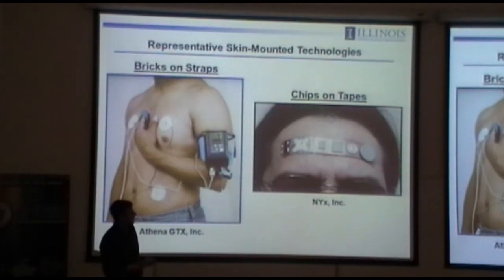You get a little bit better if you take that box of electronics, crack it open, and pull the chips out. You can mount them on a flexible PCB tape, a piece of polyimide, and then adhere that to the skin. People have thought about this. This is an actual working device, not just a vision or a concept. This is a little more sophisticated, but it's still deficient because the properties of the tape are not matched to the properties of the skin, and so it creates discomfort and an irritating interface to the skin.